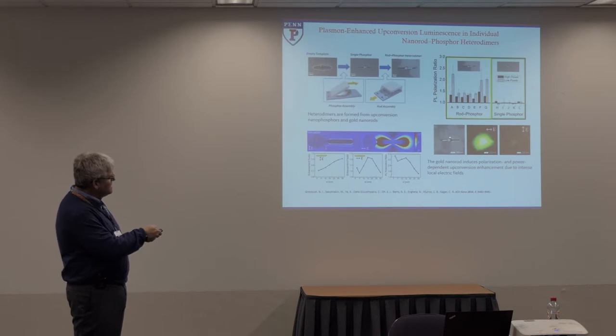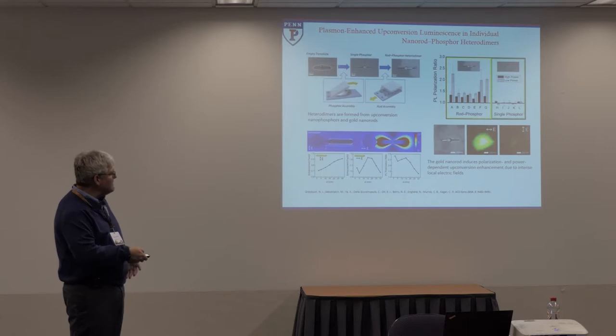So otherwise, we might not know why there was a stronger response than we had predicted for the system. This is the polarization data. If you excite in this plane, it couples very efficiently to the resonator, and you get a very large enhancement in the two-photon upconversion of the rare earth.